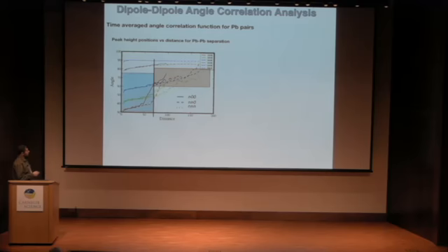So at high temperature, 700 to 600, there's absolutely no correlation. Everything's disordered from 0 all the way out to 150 angstroms, as you'd expect. But what happens when you go to lower temperatures is there's a split between a region of high correlation, where correlation grows very quickly as you cool down, let's say in this case to 200 Kelvin. But in this region, let's say beyond 60 angstroms, the correlation is there. It's not 90 degrees over here.